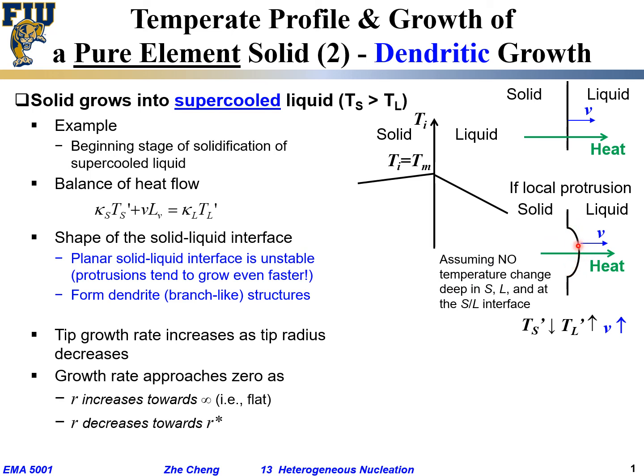The other condition is when the local tip becomes too sharp — if it becomes smaller than the critical radius, then based on what we learned about critical nucleation, the local solid would have a tendency to dissolve back into the liquid, and dendrite growth would also stop. So this is the situation of growth of a pure solid element into a supercooled liquid, where dendrites appear and grow faster and faster until the tip becomes too sharp and risks being dissolved.